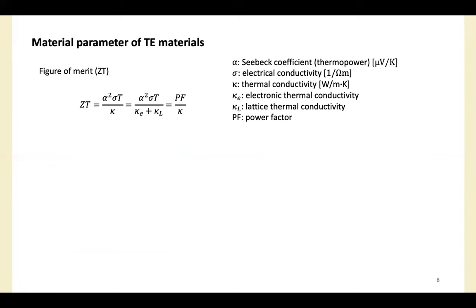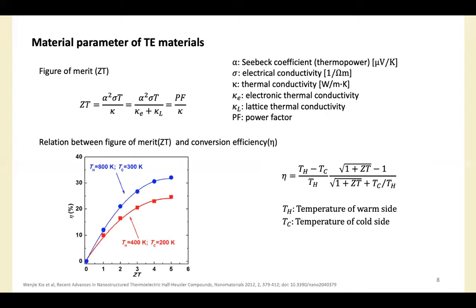In this slide, I want to elaborate on material parameters of thermoelectric materials. Figure of merit, denoted by ZT, is the primary parameter of the thermoelectric potential of a material. It is dimensionless and is expressed mainly by three parameters: Seebeck coefficient, electrical conductivity, and thermal conductivity. The thermal conductivity is composed of electronic thermal conductivity and lattice thermal conductivity. The exact equation is written here.